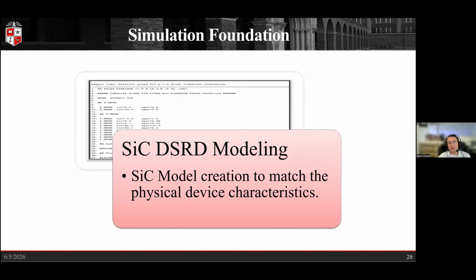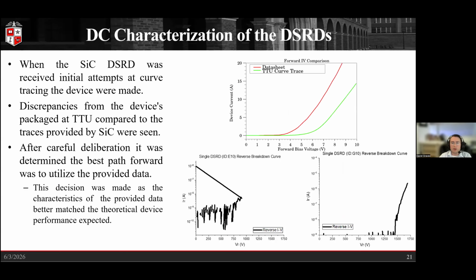And so now we'll talk a little bit about the initial work that started all of this. So one of the things that we did was we were provided with a silicon carbide DSRD from Sandia National Labs. With that, the intended goal was to create a model to match the physical device characteristics. And so that began by doing some curve trace comparisons, right? So in this plot here, we're looking at some of the differences between what was provided from the manufacturer on their data sheet versus what we were ever able to achieve. So some slight discrepancies in that, likely due to some of the different packaging methods they may have used when characterizing the device on the fabrication side.